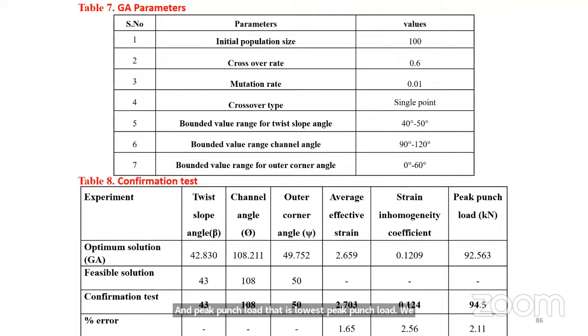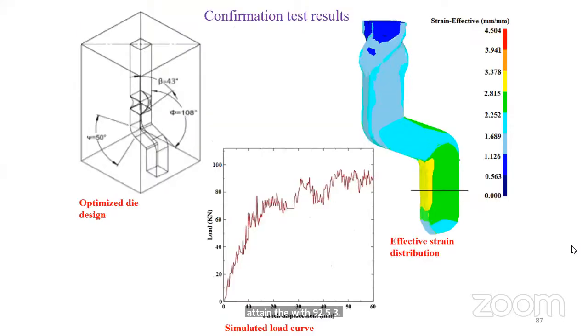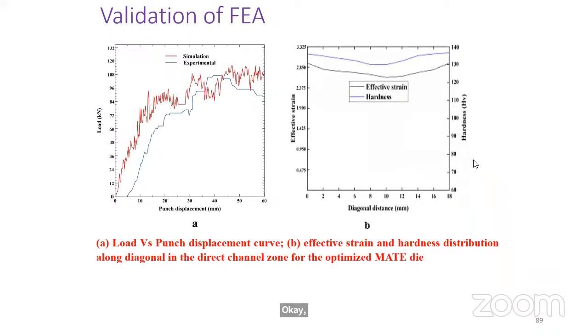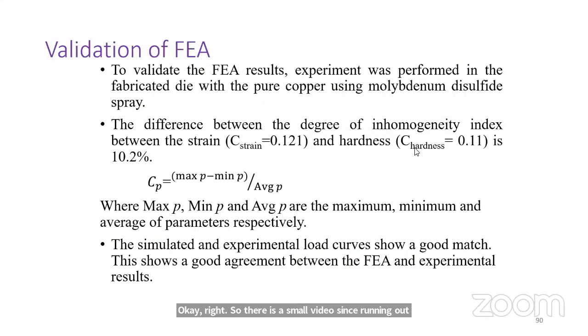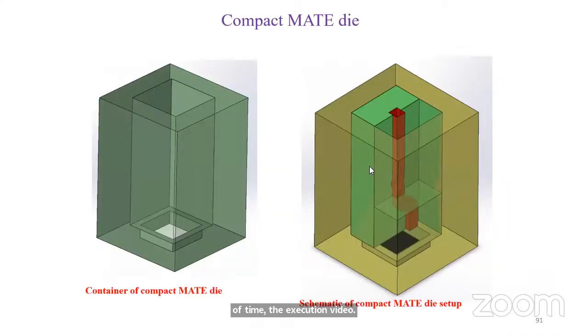We have conducted a confirmation test also, and we found the percentage error is very, very minimum. So we have developed the die based on these parameters. We can see the effective strain is 4.5 with this effective strain distribution using the optimized parameters. There is a small execution video, but since I'm running out of time, I'm skipping that one. We have validated with the FEM model.